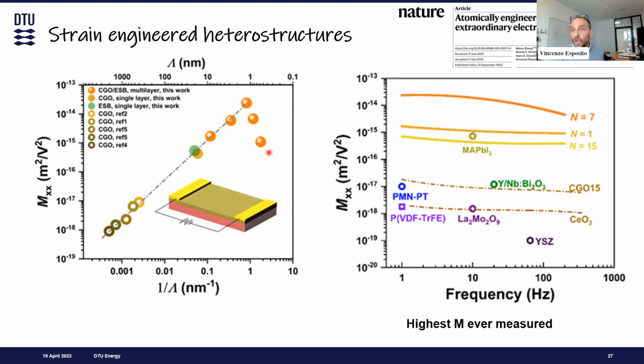But I think what is interesting to notice here is that the electrostriction that we get in this material is much higher than anything ever measured among ceramic materials, and not only ceramics actually. You can maybe recognize here a few polymers and relaxor ferroelectrics, and even new materials that have been tested electromechanically just recently. These results, of course, are very interesting, and since they are so important, we could publish them in Nature.